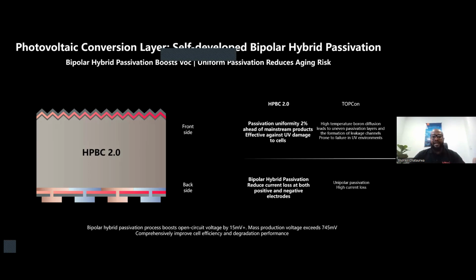When we did an experiment, we found out that the passivation uniformity is 2% ahead of the mainstream product, which is effective against UV and protects the cells. We also have the advantage that the passivation reduces current loss at both positive and negative electrodes. So by placing passivation on both, that's where the name came from, bipolar. Bipolar hybrid passivation, that's where it came from.